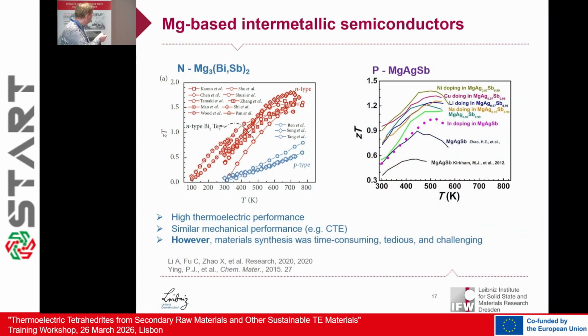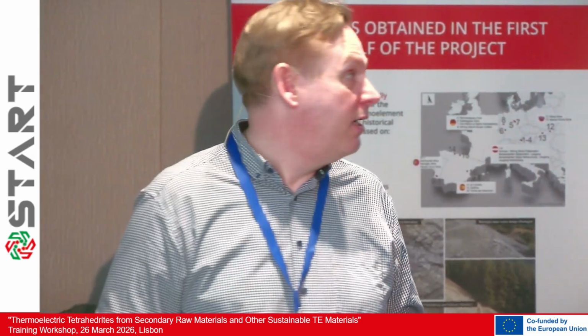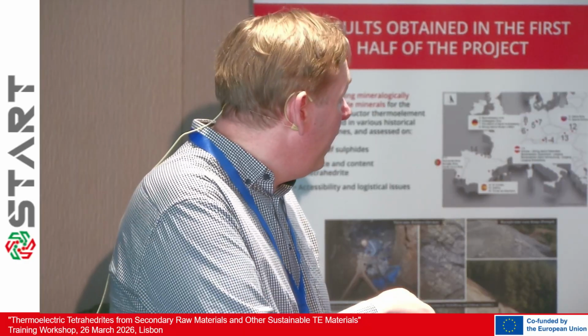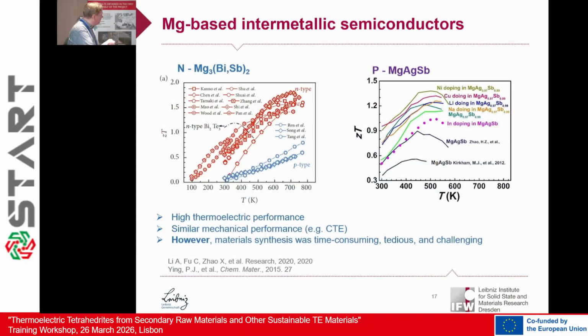So our strategy is to use these two compounds, starting with magnesium bismuth antimonide. You see very high performance here around room temperature. This is the N-type material, very promising. For a very long time it was known that it could be a very promising material, but people had not figured out how to solve the issue of losing magnesium during the fabrication process. Nowadays, you usually work with an excess of about 10–20% of magnesium to stabilize the compound during hot pressing, and this helps to reach these high ZT values.